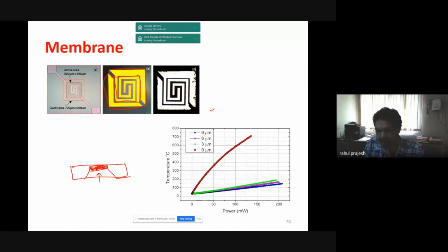Now we are trying to vary this membrane and observe what temperature we are getting at different powers. Now when we have 9 micron silicon left on the back side of the micro heater, you see the temperature for about 100 milliwatt is only close to 100. So for 9 micron, 6 micron, 3 micron, you will see only about 100 degree temperature is achieved. But if you remove the complete silicon from the back and only the oxide membrane is remaining, you see a very huge change in temperature. And at a given power, almost 600 degrees centigrade you are able to achieve. So that's the advantage of removing silicon from the back and reducing the thermal mass.